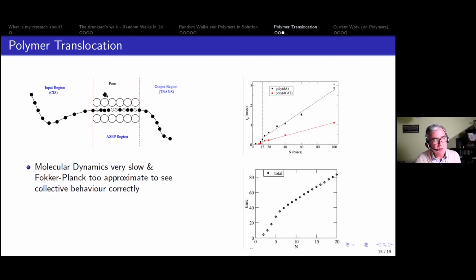And our idea was to look at the dynamics within the pore as an asymmetric exclusion process, a hopping particle model in 1D. And then this feeding rate, alpha, is determined by the average behavior, the approximate behavior of the number of monomers that's left in the input region, in the cis region. And the beta, the rate of pulling particles out the other end, is modeled by the number of monomers that are found in the output region.